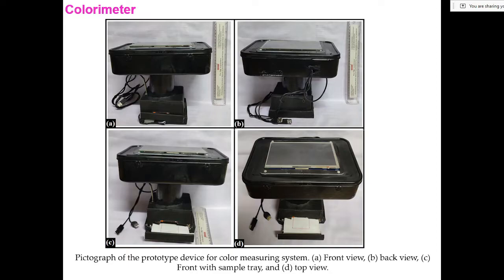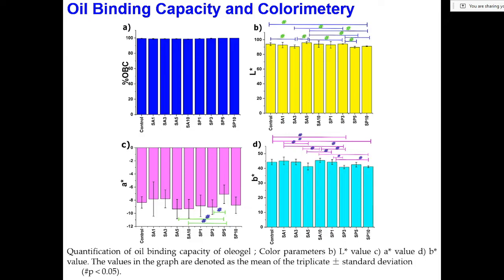Now, one of the important parameters while we develop any kind of formulation is the color parameter. So in our lab we have developed a colorimeter indigenously. If you try to procure such a colorimeter, it costs approximately 2 lakhs and may go as high as 12 to 15 lakhs. However, in our lab we were able to develop it at only 15,000 rupees. Okay, so the principle is very simple, which I will not go into the details of over here.